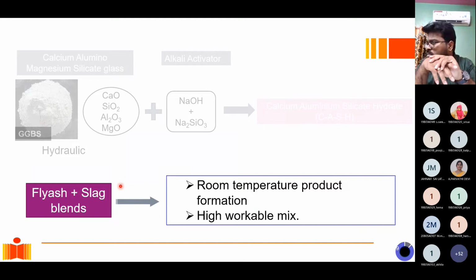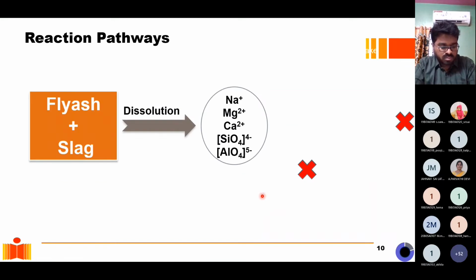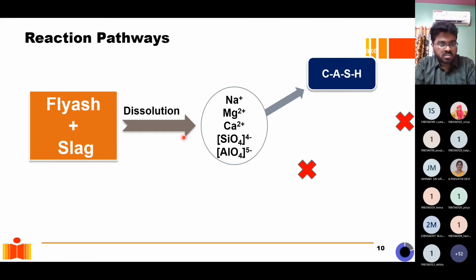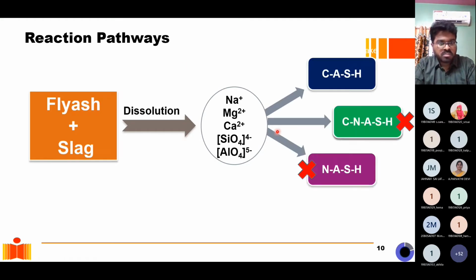What we are working on are blends of fly ash and slag to overcome the limitations of both. I'll show the limitations of what these binders have. So we blend fly ash and slag. Remember, both are waste materials. We alkali activate them, and what we're able to get is a binder which basically sets at room temperature, gives us strength, and it's a highly workable mix. So now, when we have fly ash and slag and we subject it to alkaline dissolution, the chemistry becomes quite complex, and we've understood this.